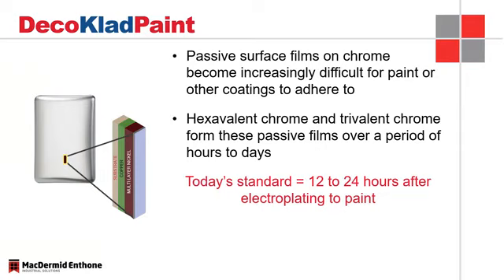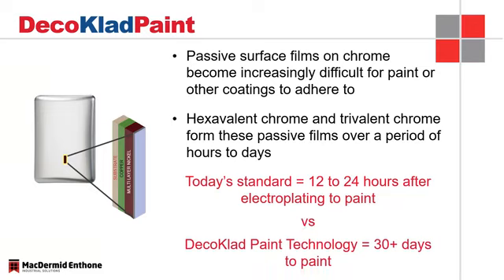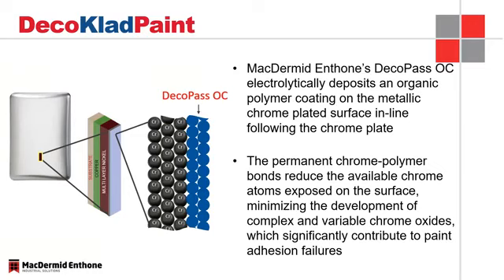And so that has been the reason for the OEMs to specify a very tight plate to paint window: 12 to 24 hours after electroplating, those parts need to be painted. If an applicator incorporates the DecoKlad paint technology into their system, I can go 30 days or more between plating those parts and having to paint them. So significant increase, obviously, in that plate to paint window. And that's a direct result of adding in the DecoPass OC process, that organic coating step. What happens in this instance is that I'm electrolytically depositing this organic polymer over the chrome surface immediately following the chrome plating step. So I go into my chrome plate, I rinse, and I go directly into my organic polymer, that organic coating.